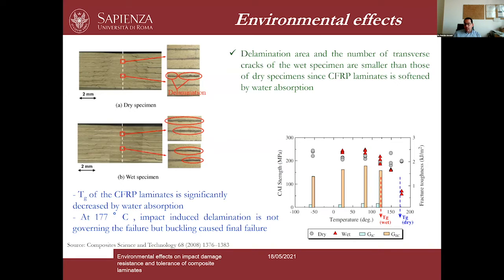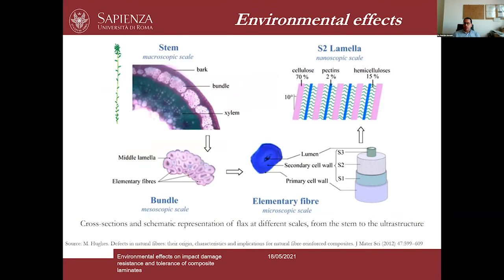Okay, and so the damage was completely changed. And this is important to highlight because, as I showed you, in this specific case, for conventional composite material, the level of water absorbed was pretty low. And this is expected to be much more significant when we deal with natural fiber composites. And firstly, because natural fibers show some peculiarities in their microstructure and in their mechanical properties.